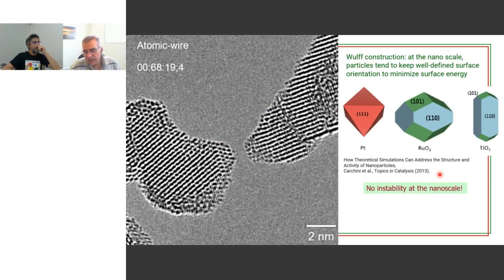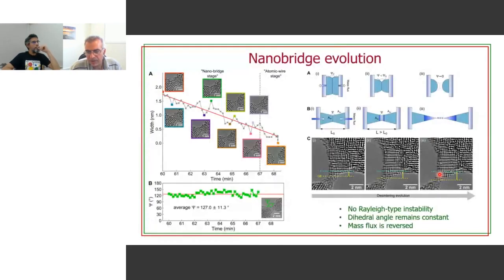And this is the take-home message. There's no instability at all at the nanoscale. So this is very different from the classical description. And also the dihedral angle is roughly constant throughout the process. So let us analyze these two facts in a more quantitative way. This is a plot of the width of what we call the bridge, the interface between the two nanoparticles, as a function of time. It's roughly linear. There's no instability. And this is a plot of the dihedral angle as a function of time. It's roughly constant, right? So, okay, these are the experimental data.